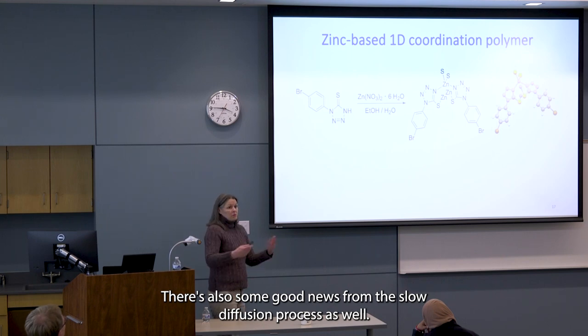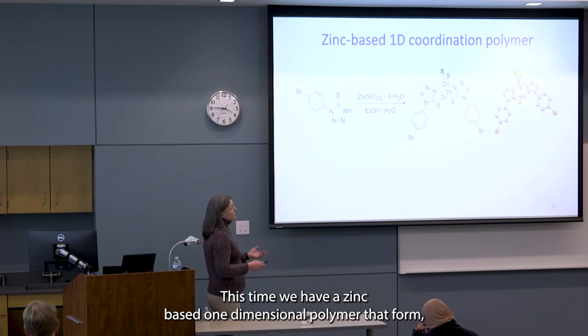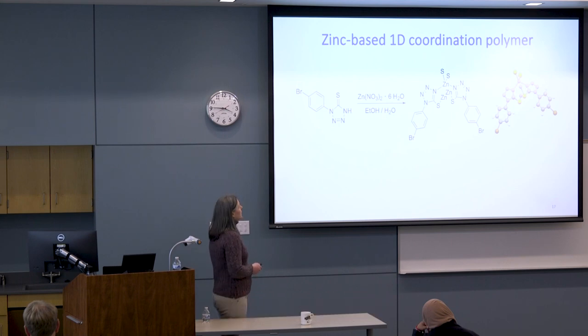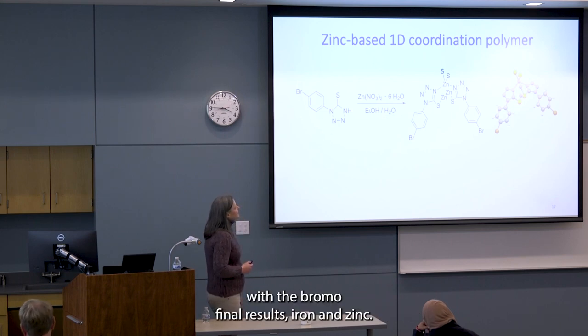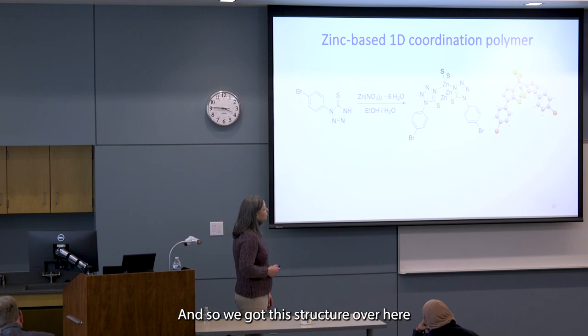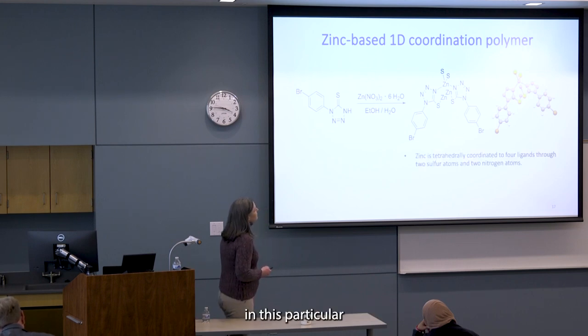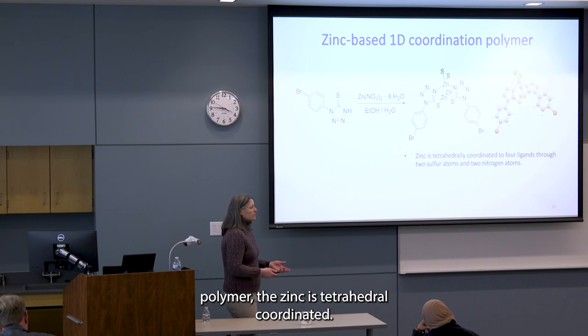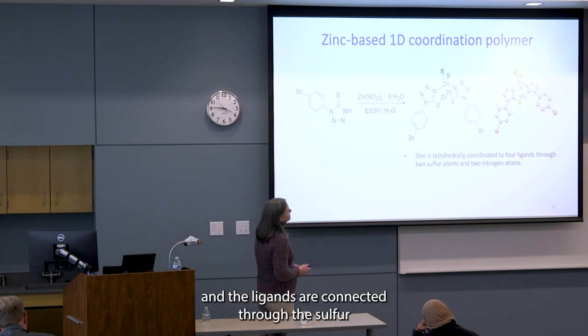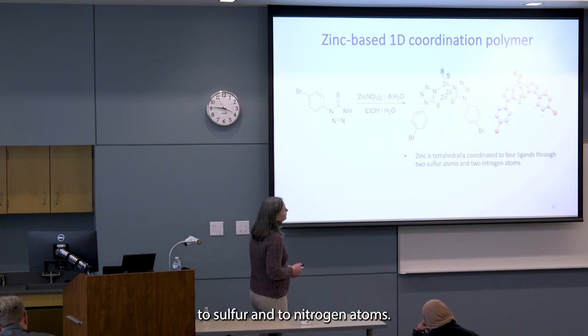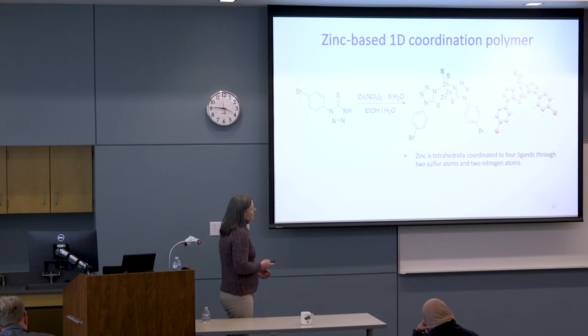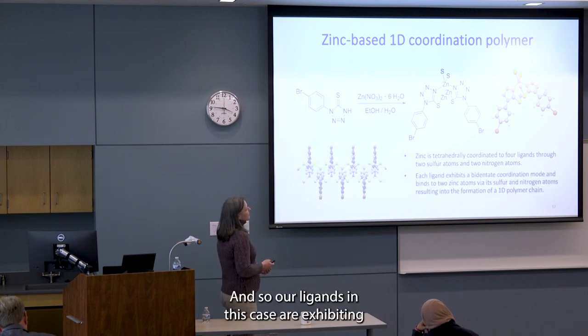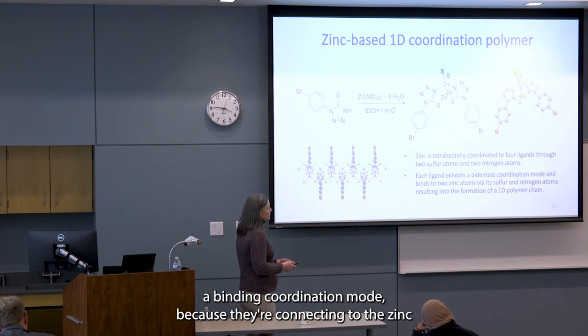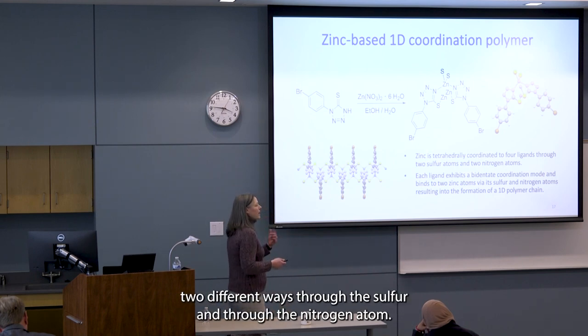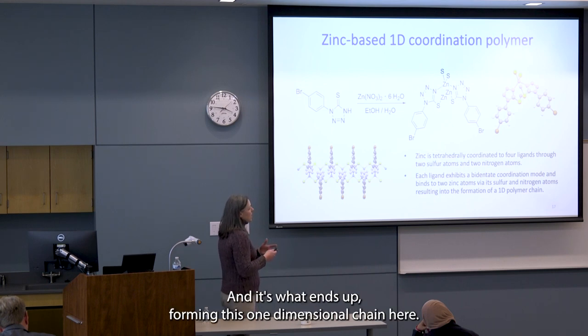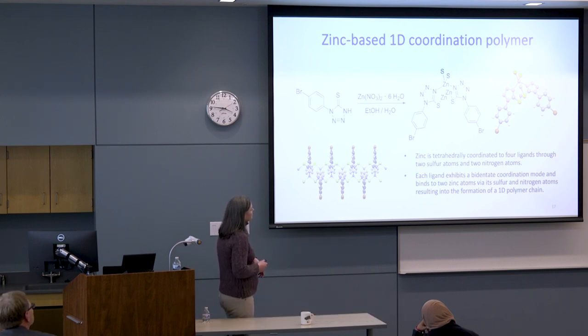There's also some good news from the slow diffusion process. This time we have a zinc-based one-dimensional polymer that formed with the bromophenyl tetrazole thione and zinc. And so we got this structure over here. In this particular polymer, the zinc is tetrahedrally coordinated, and the ligands are connected through two sulfurs and two nitrogen atoms. Our ligands in this case are exhibiting a bidentate coordination mode because they're connecting to the zinc two different ways, through the sulfur and through the nitrogen atom, and it's what ends up forming this one-dimensional chain here.